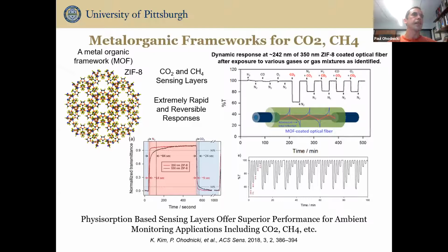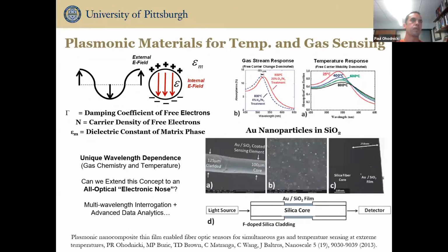The unique aspect about integrating sensing layers on a fiber is, though, so notice that on this slide I don't say whether it's point or whether it's distributed. The reason for that is that in the case of optical fibers, in principle, a sensing layer could be either a point measurement, or you could expand it to a distributed measurement by combining that with distributed interrogation methods. So you have the ability to choose whether you just measure at one point or whether you measure all along the length of a pipeline, for example.